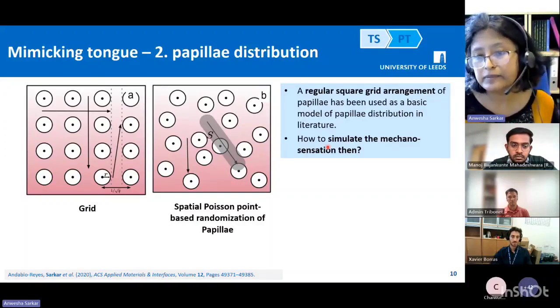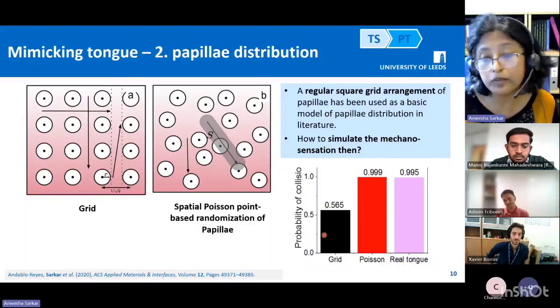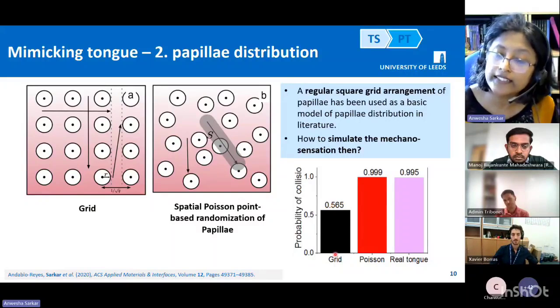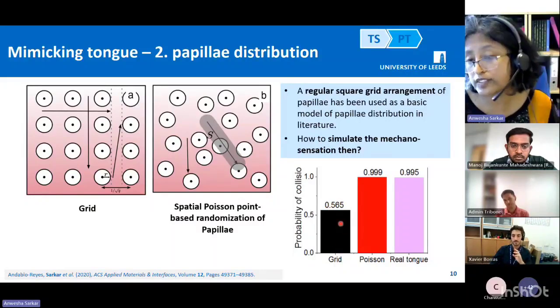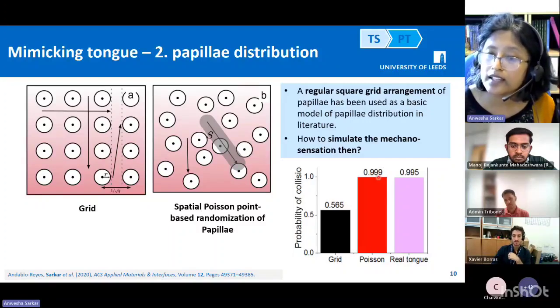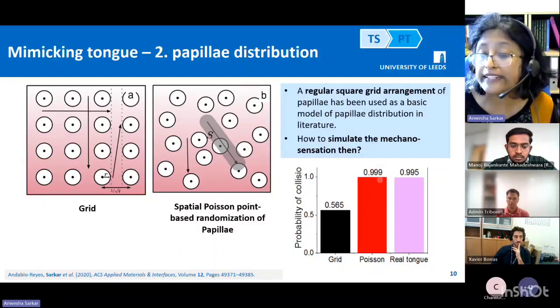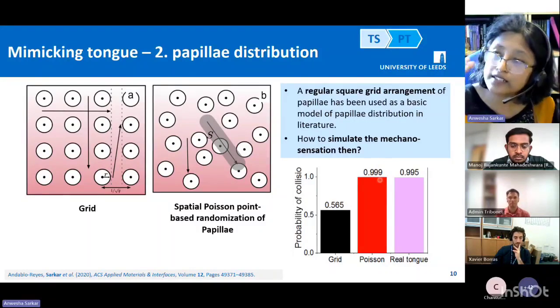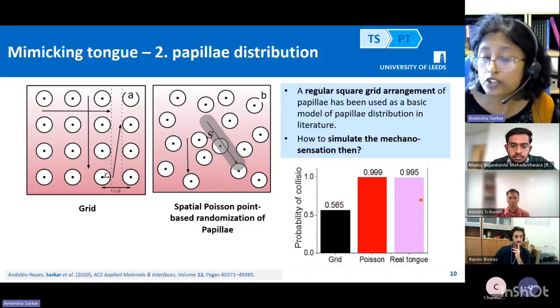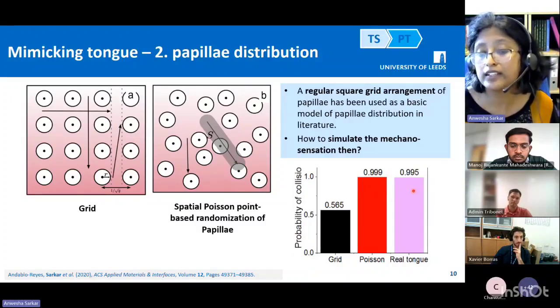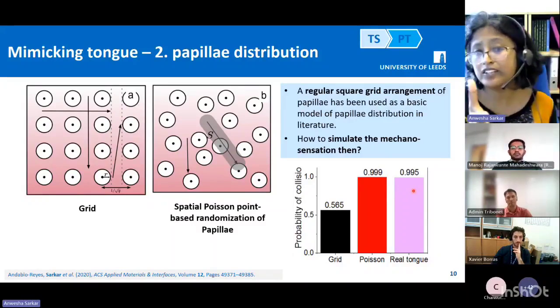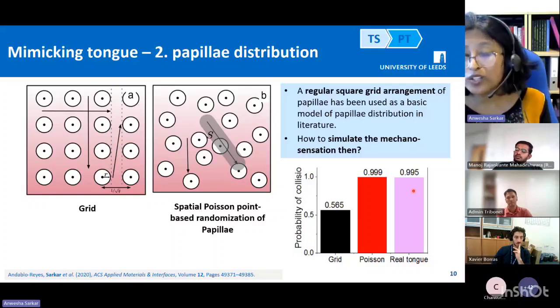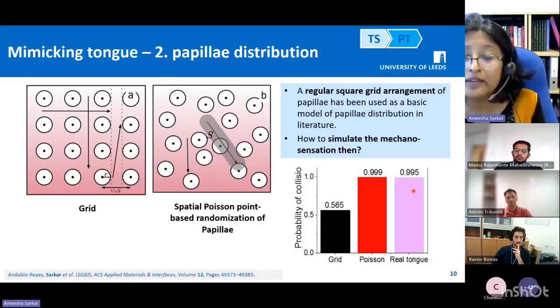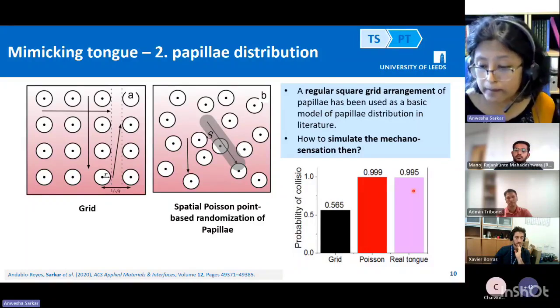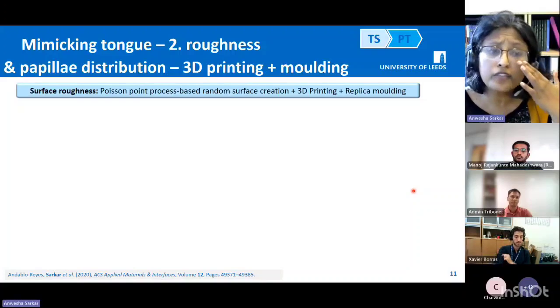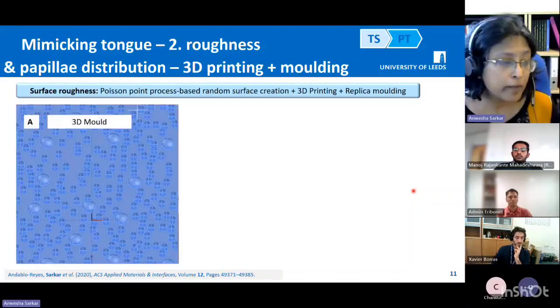So with that, we created this model. And we did some computational work and saw that if you do a grid, the chance of mechanoreception is 50%, 56%. But if you do a Poisson point process, you have a distribution in the order of 99.9% chance of a particle in a linear line hitting the papillae, which is actually similar to a real human tongue mask. So we are pretty confident that this kind of distribution works, and not only works, it's congruent to what happens in mechanoreception. It resembles what happens in a real human tongue.